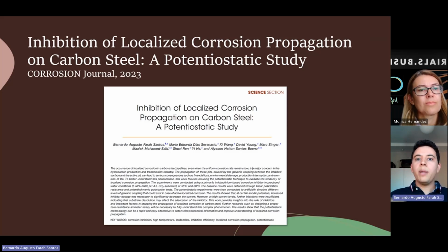So we applied different sets of potential using the potentiostatic technique and injected the inhibitor into the environment, because the inhibitor will naturally tend to adsorb to the active surface of the pit, that in this case is our working electrode, and the corrosion inhibitor would mitigate or not. So our parameter was, if the current that we observed after applying the potential starts dropping after the injection of the inhibitor, it means that the inhibitor is adsorbing on the actively corroding surface. That would tell us that for that particular environment, the inhibitor was able to mitigate the propagation of localized corrosion by this galvanic cell that is established.